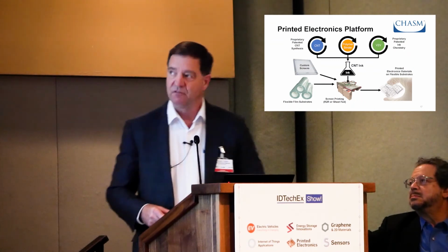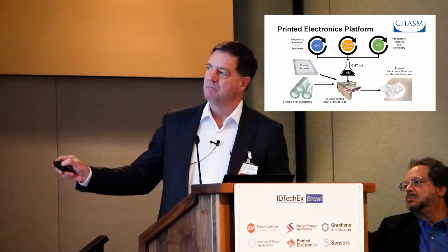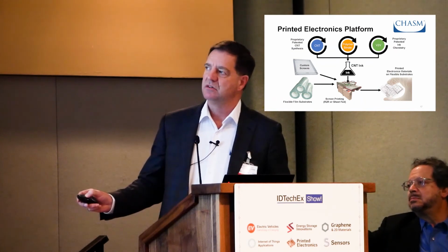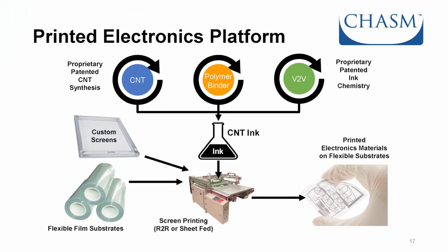Our printed electronics platform is that we make all of our own carbon nanotube materials. We have proprietary ink vehicle technology. Both our carbon nanotube synthesis and our ink chemistry are patented. The ink technology is called V2V, viscous fluid transitioning to vapor. We synthesize this ink vehicle to make a high molecular weight, highly viscous material. But at 80 degrees C, it decomposes to its precursors, which at 80 degrees C are volatile. So this ink vehicle completely evaporates at 80 to 100 degrees C, which is low enough temperature for the plastic film substrates.